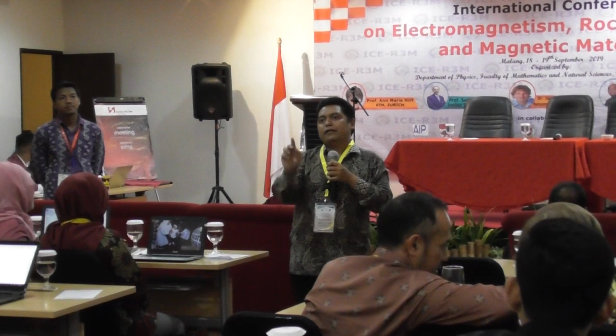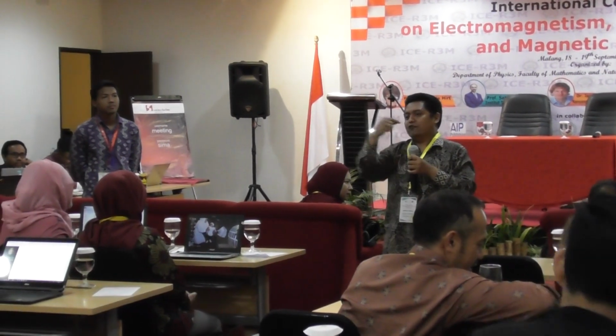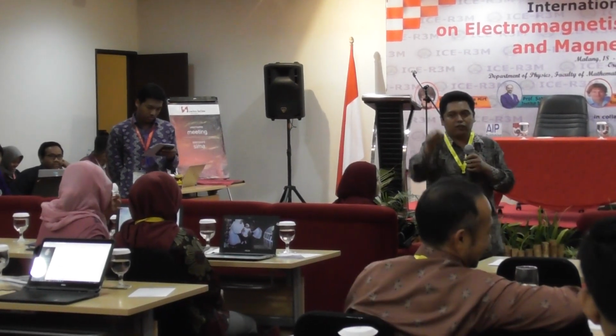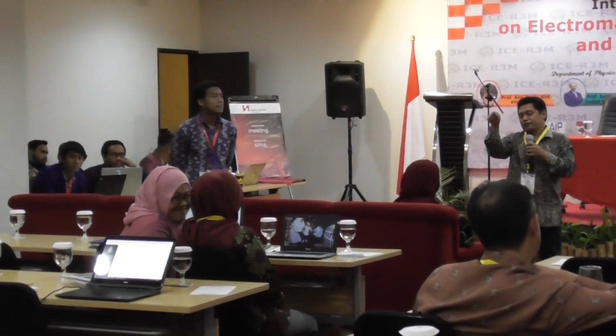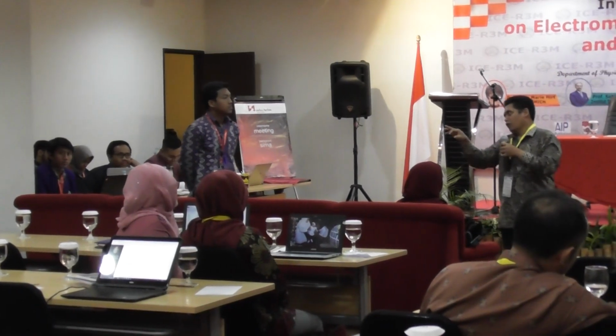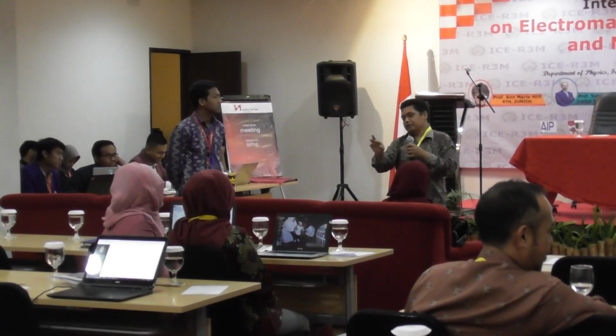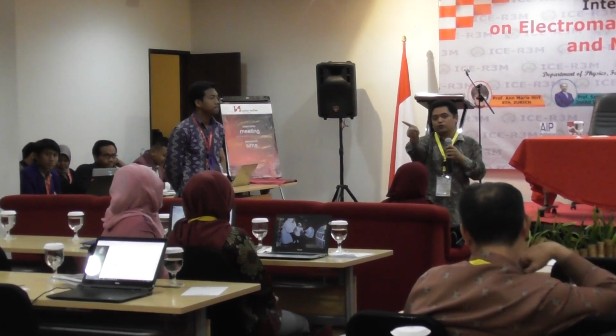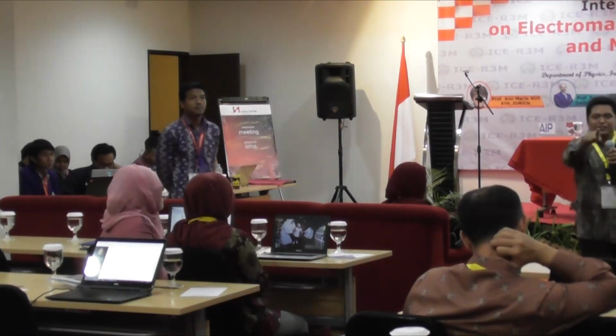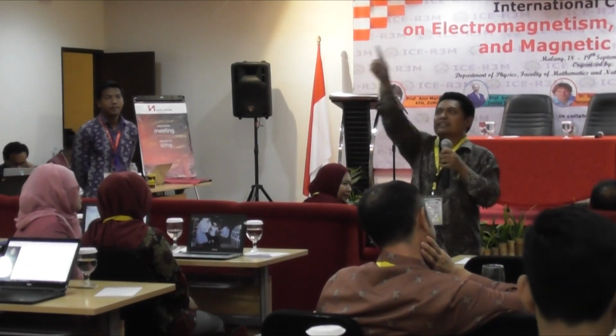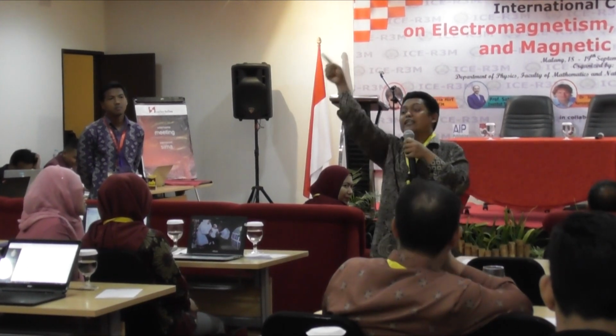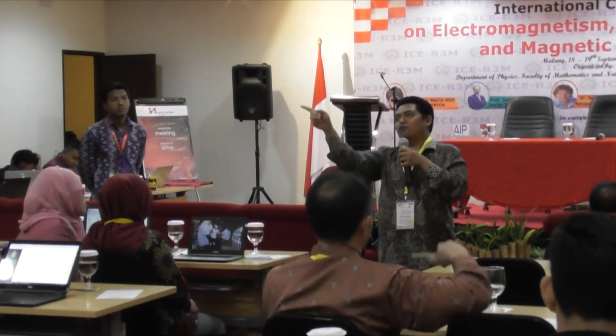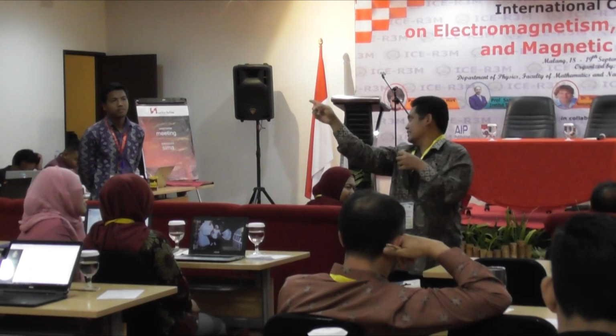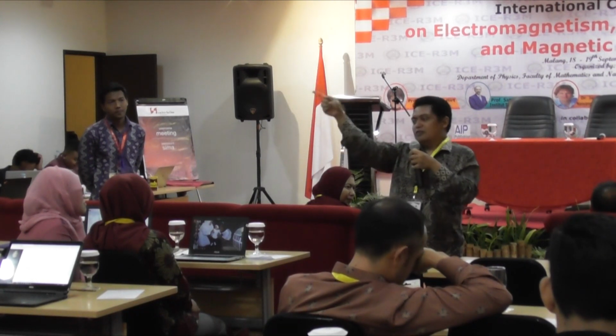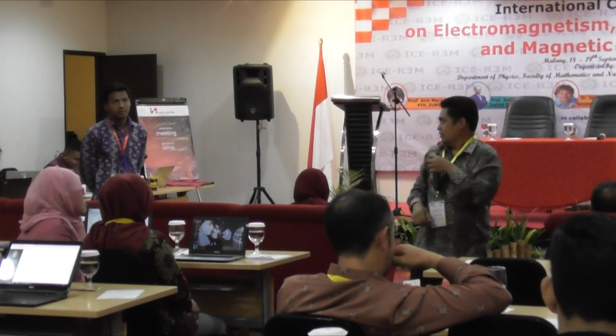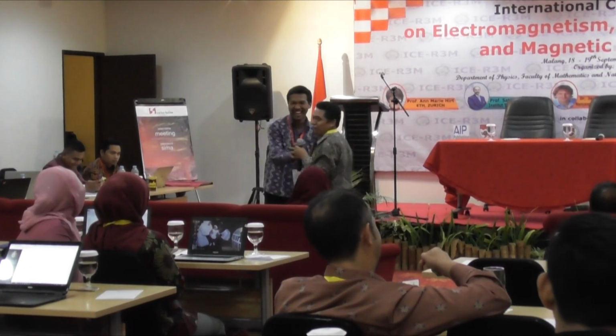For antiferromagnetic, the spin up and down are similar, so there is a cancellation. For superparamagnetic, because of the quantum effect, Dr. Reni can explain. Because of the particle size, the ratio of the surface and volume gives a quantum effect. So the ferrimagnetic will move to the superparamagnetic. Actually, like Professor An's presentation, he showed good data. The first one has hysteresis, but not very thin, like your presentation, and the second one for the superparamagnetic is very thin, with no hysteresis. So the data will go back to the initial position. You can join my S1 magnetic course every Wednesday.